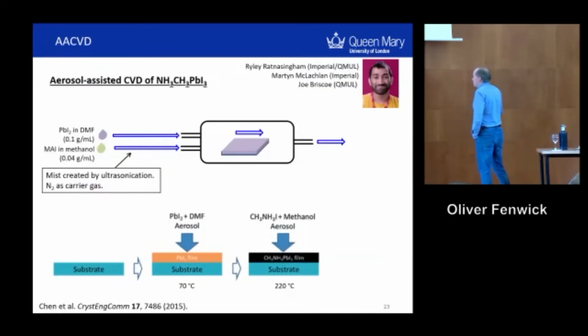We also explored different morphologies for the same materials. This is methyl ammonium lead iodide again, but deposited by aerosol-assisted CVD. This is being developed at Queen Mary's and at Imperial for producing halide perovskite solar cells in a more scalable way. Essentially they carry the precursor lead iodide as an aerosol deposited on the film and then react it with the methyl ammonium iodide. And this allows you to go to much bigger film thicknesses as well as doing batch processing at wafer scale.